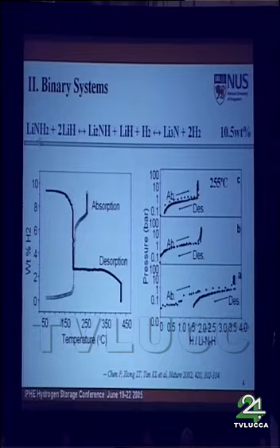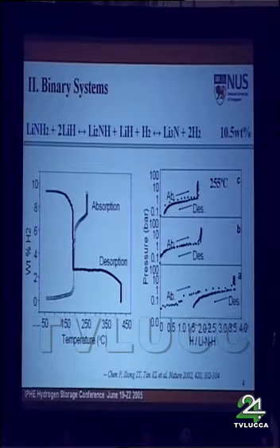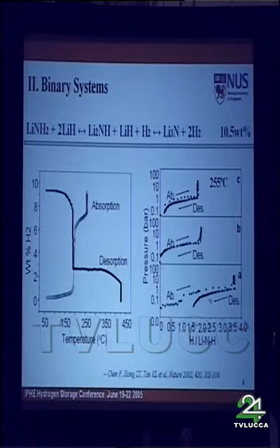First of all, let me introduce the lithium nitrogen hydrogen system. If we start from lithium amide and lithium hydride, we will go to lithium imide. It's a low hydrogen state compound, lithium imide. And if we mix lithium imide with lithium hydride again, we will finally get lithium nitride. It's the lowest hydrogen content state. But during such a chemical reaction, we can see roughly more than 10 weight percent of hydrogen desorbed from the starting material. And the temperature for the desorption, you can see from this chart, is roughly about 150 degrees Celsius. It's a two-stage desorption process. And by the PCT measurement, we can say to achieve 1 bar equilibrium desorption pressure, the operating temperature has to be about 250 degrees Celsius. This is the lithium nitrogen hydrogen system.